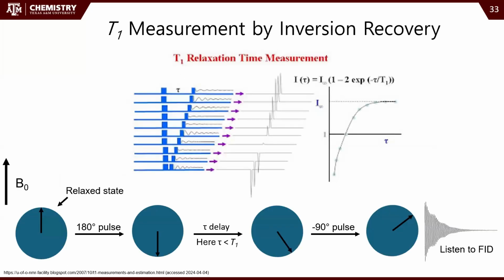So measuring T1 is pretty straightforward. We used inversion recovery. So if you imagine this is the superposition of the nucleus, and that's kind of the axis that it's rotating on, it is usually in its relaxed state aligned with the magnetic field. And then we give it a 180-degree pulse, and then we wait some time tau. And as we're waiting, it will do T1 relaxation, which is kind of what I've drawn here, which is going back up to the relaxed state. And it will also do T2, and so that's starting to decohere the signals. Okay, so that's going to shorten our FID. So we wait some time tau, and then we do a negative 90-degree pulse. And so that flips it up. And importantly, it reverses all of the T2 relaxation.